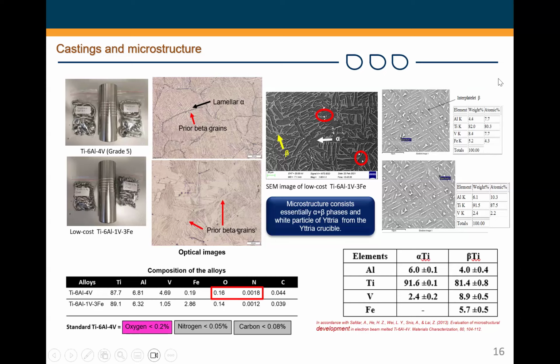And we were able to use EDS analysis to confirm which phase is alpha and which phase is beta. So alpha is the HCP, hexagonal close pack structure, and the beta is more or less the BCC structure. The reason why we want the BCC structure is that it allows for easy processing of titanium alloys compared to the hexagonal close pack structure, and that's why you want the combination of both, so it gives you good strength and ductility at the same time.